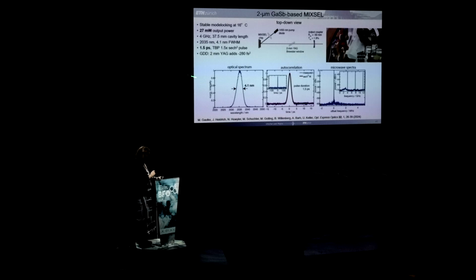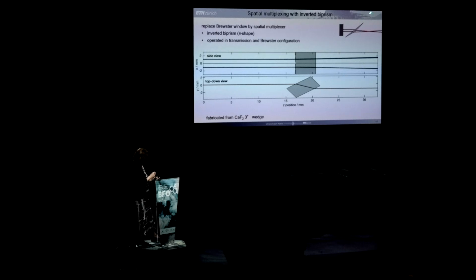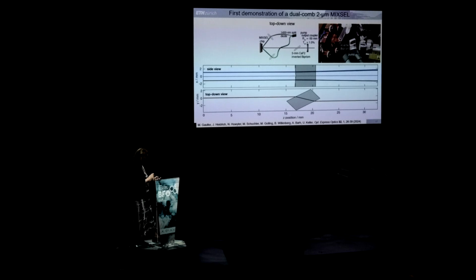So we then did the mode locking out of this laser with 27 milliwatt output power, which for spectroscopy application is plenty. And the repetition rate is in the gigahertz with picosecond pulses. And then, next slide, we added here a spatial multiplexer, basically a nearly flat calcium fluoride window, but it has a little bit of an inverted biprism here, which is only 3 degrees, but this basically makes the linear laser cavity stable for 2 beams with slightly different path lengths. And with this, we obtained then a dual-comb mode-locked MIXSEL. Next.